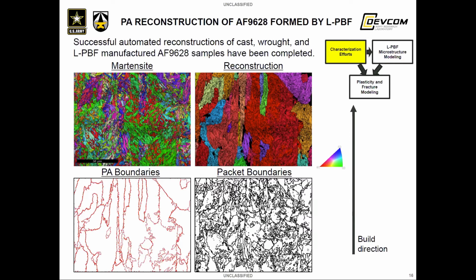Either way, the directional anisotropy of the austenite grain boundaries is immediately apparent, as shown in the bottom left image. The messy packet boundary structure shown in the bottom right is shown as well. The packet boundaries are a bit more equiaxed than the parent austenite structures, which is a little thing of note. It's possible that the anisotropic arrangement of parent austenite boundaries would introduce some form of anisotropy in the plastic behavior of this material. If so, that would be an interesting and viable means to manipulate the mechanical behavior of the part through laser powder bed fusion.